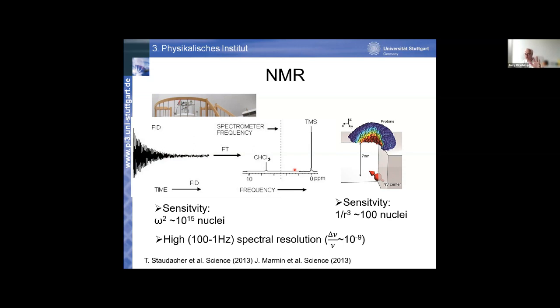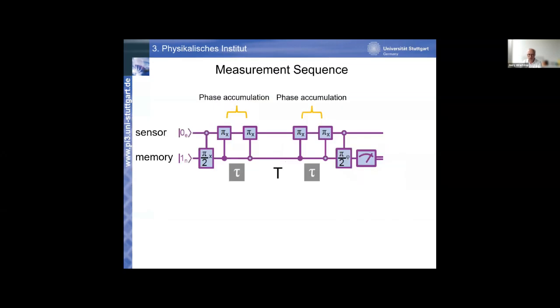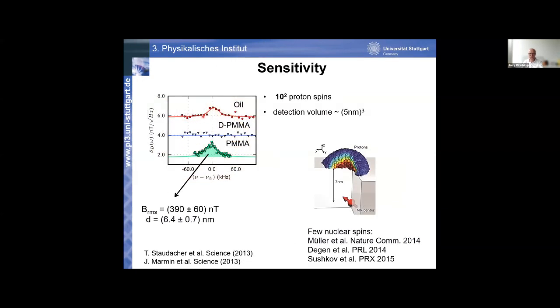All right, now let's see if we can do something similar. And well, maybe I go two slides back to highlight the problem. Well, if you look at our spectra here, we are measuring Larmor precession, so it's exactly like the classical NMR, nuclear magnetic resonance spectrometer, is operating. If you look at the line width here, you see that this scale is kilohertz. So the line width here is on the order of a few kilohertz. And why is this so? The reason is that the relaxation time of the sensor electron spin is on the order of milliseconds, right? This is the T1 time or the T2 time we had. It is limited at room temperature.